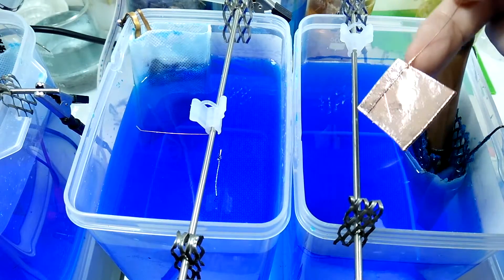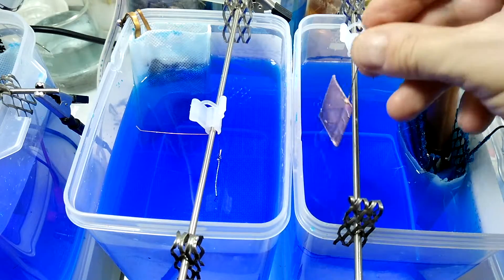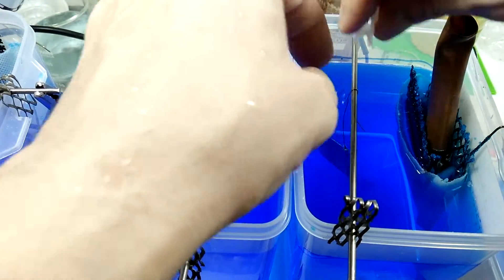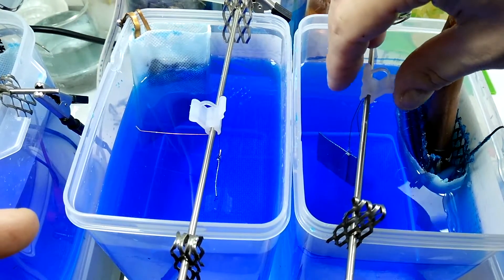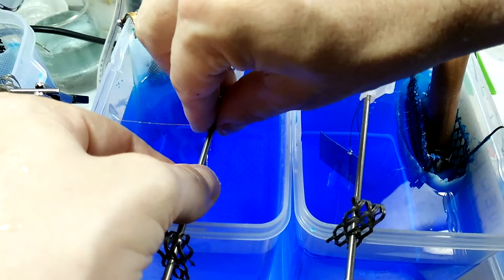We're at the two hour mark and it's been going at full current for about an hour now. Everything looks really good — it's bright and shiny. We have really good detail. At this point you can decide to stop the test because you've shown that you can successfully electroplate a leaf. I'm going to continue this test — I'm going to bring the amps up to 0.22 amps and then leave it overnight, so we'll see what the finished product looks like: a fully electroformed leaf.